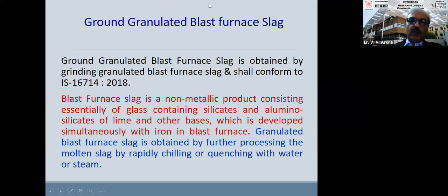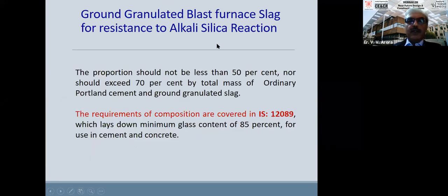This is a very good material for concrete and cement, and this can directly replace cement up to 50% and even up to 70%. Our Portland slag cement has this provision of 50 to 70%. So either people use Portland slag cement, or it can be used in concrete also, wherever required at site mixing, where proper mixing is possible.